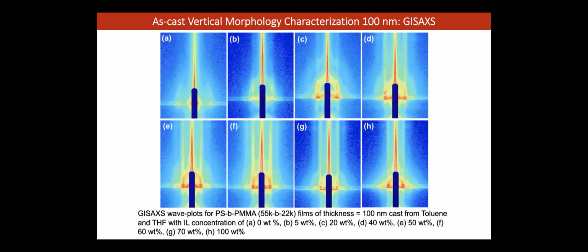And when you see these, as you go to C through F and higher, in fact H, you see the isotropic ring come up. That means that you have cylinders or lamellae, whatever it is, that are now meandering in the in-plane structure of the film, which would bring about tortuosity to the membrane. In fact, we should think about as a community how to take these isotropic scattering profiles and do some average cuts, maybe in a radial direction, to figure out if we can actually get that tortuosity value. It's a mathematical definition. What is tortuosity for a membrane?